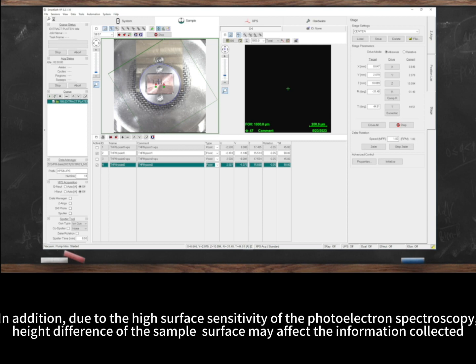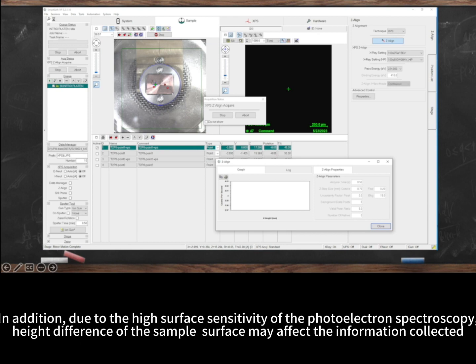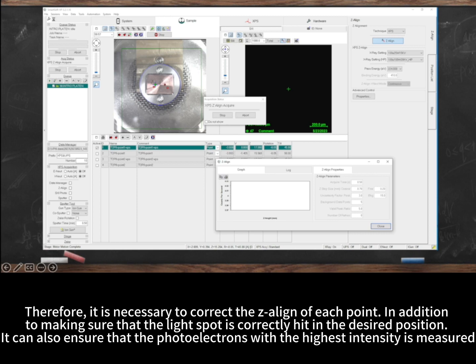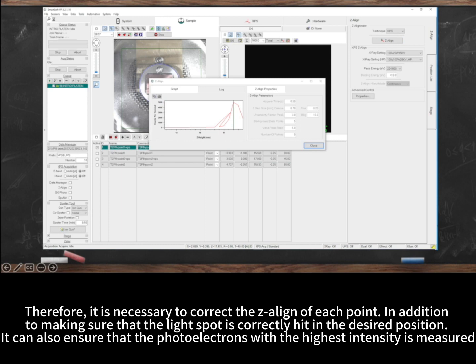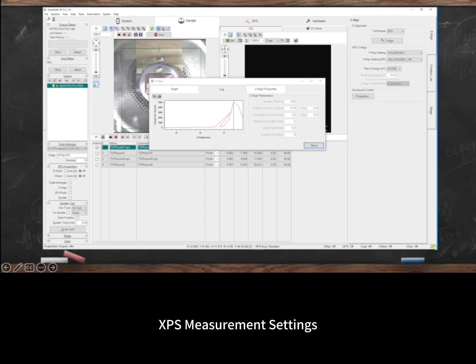In addition, due to the high surface sensitivity of photoelectron spectroscopy, height differences of the sample surface may affect the information collected. Therefore, it is necessary to correct the z-align of each point. In addition to making sure that the light spot is correctly hit in the desired position, it can also ensure that the photoelectrons with the highest intensity are measured.